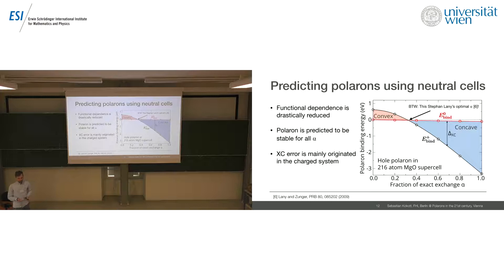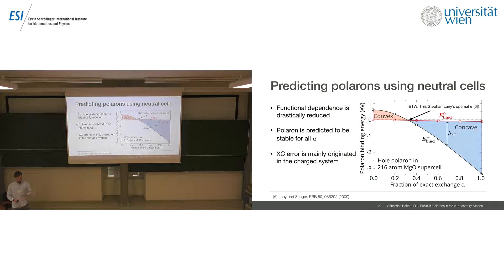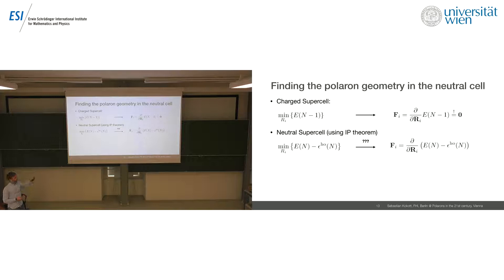What you can also see, based on the assumption that a large change in this quantity indicates dependence on the exchange correlation functional, is that the exchange correlation error is basically originated in the charged system - which is somewhat understandable, because the neutral system, magnesium oxide, is basically a closed shell system. When you remove a charge, you open your closed shell, and all the problems start that are well known in the field of density functional theory.